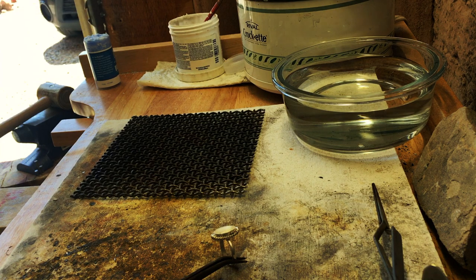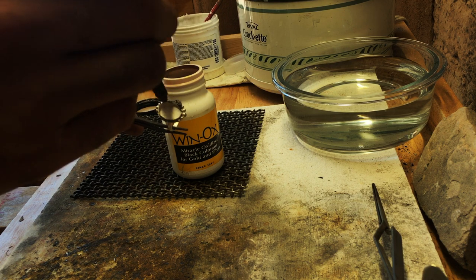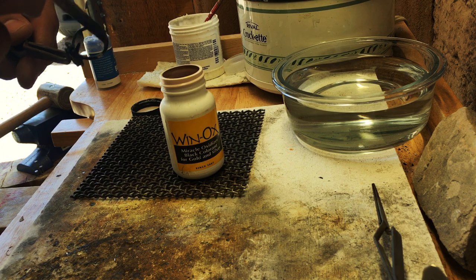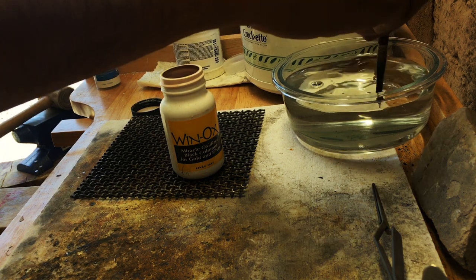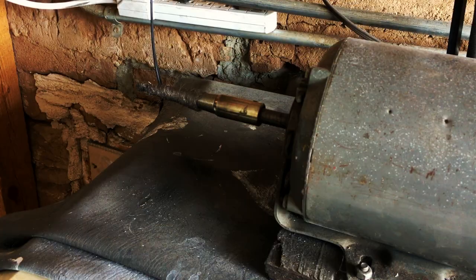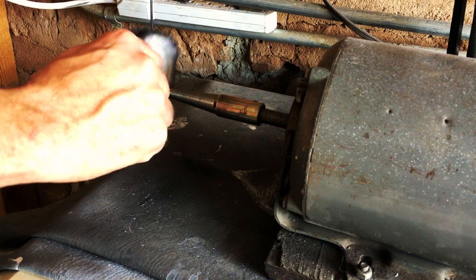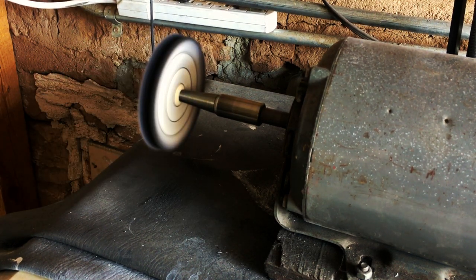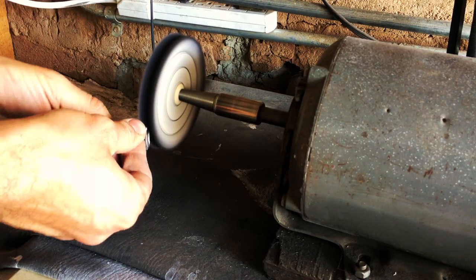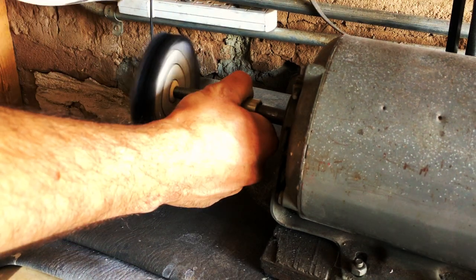After you pickle it, there are two things you can do: use liver of sulfur or a commercial oxidizer — I'm using one called Winox — to blacken it before polishing. I have a brush dedicated to that, which is important because the oxidizer will rust your materials. Then I use a little bit of Zam on a soft muslin wheel, using a light touch and going in both directions for the beads and rope to get every angle. Do the inside with some steel wool.